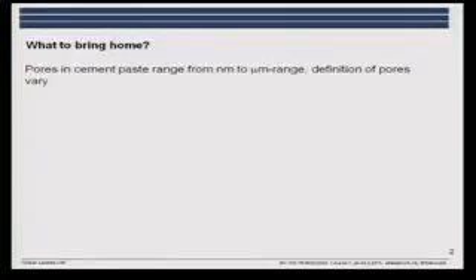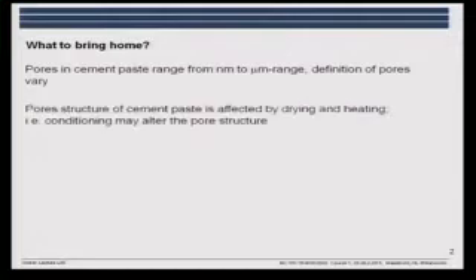You won't forget this, will you? That we have this variation in porosity and the definitions vary. That the pore structure of cement paste is affected by the drying and heating if we treat it. So conditioning, preparing your samples before you actually look at the pore structure, may alter the pore structure. And that has to be considered.